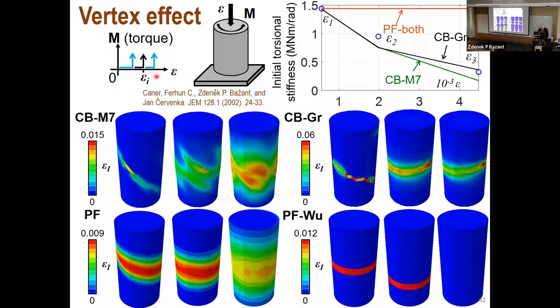And according to every model with loading surfaces, it should be elastic, except if there is a vertex. If two surfaces intersect at that point, but in compression, there are no two surfaces intersecting here. Now, this is not true, of course, and it was found already by Budiansky for metals with Drucker in the 1950s. Debated a lot, then ignored because it was an inconvenient problem. And then about 20 years ago, Ken and I showed it at Northwestern, tested it, and we showed this enormous effect, even more than for metals.